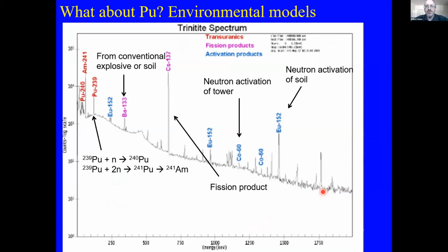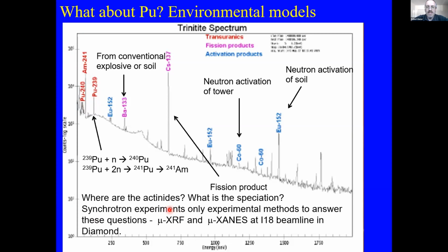So we managed to get a sample of trinitite off eBay again. This is the gamma spectrum. So we can see neutron activation products from the soil and from the tower, but also fission products and products from the conventional explosive, which was barium nitrate. But we also see in the spectrum plutonium and americium. There have been very few studies on trinitite until quite recently, and no speciation studies at all. So nobody really knows where the actinides are or what they are.